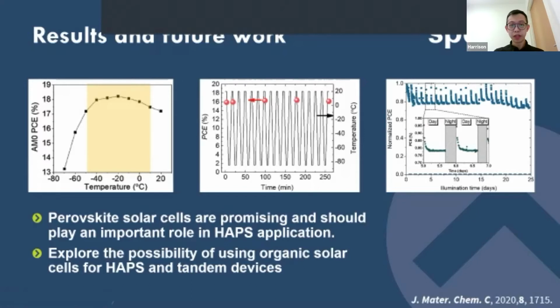And also, we find that the perovskite cell we have tested is very robust. So it can withstand rapid temperature change. You can see the black line behind is the change in the temperature. And the red point here is indicating that after several cycles, we keep testing at about 20 degrees, and the performance is still roughly the same. So no degradation, basically, against this rapid temperature change.